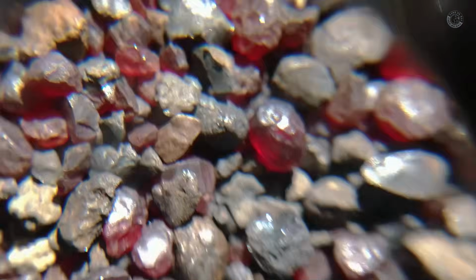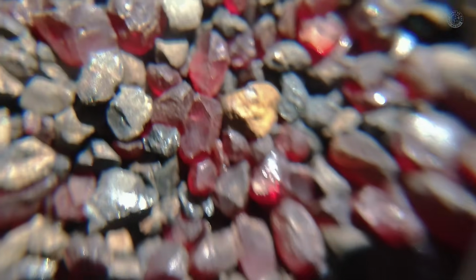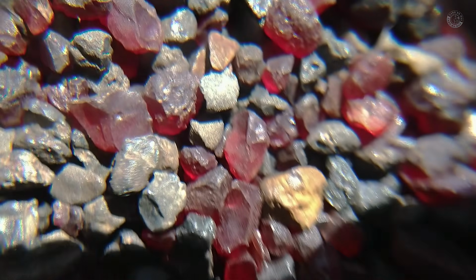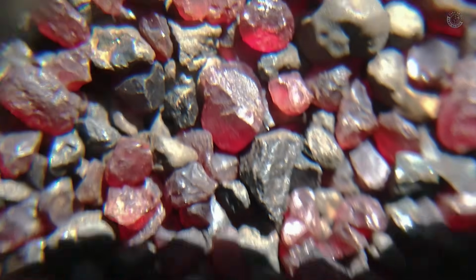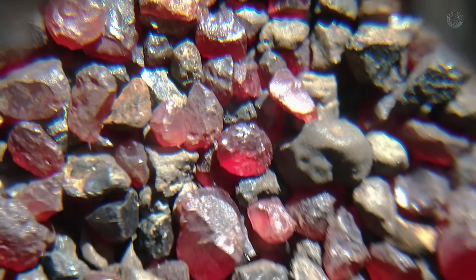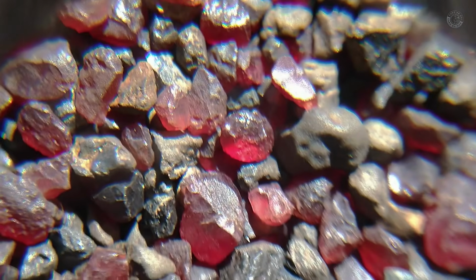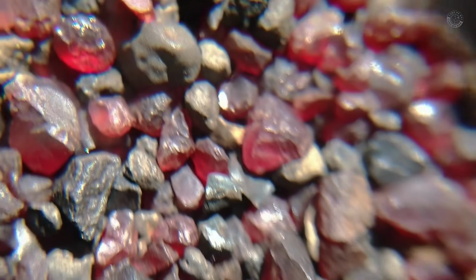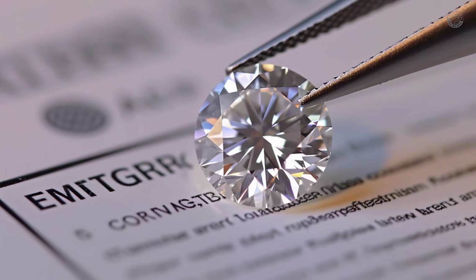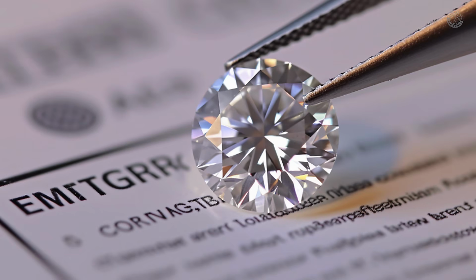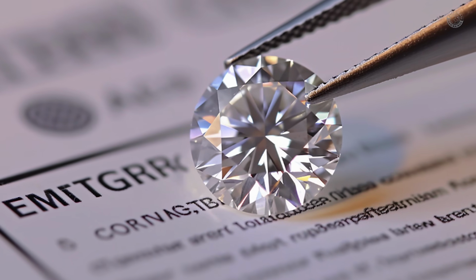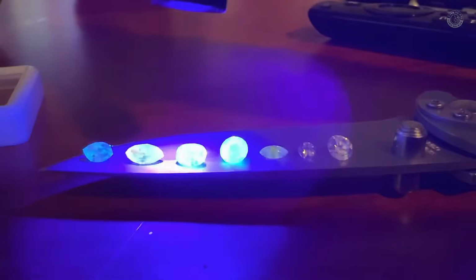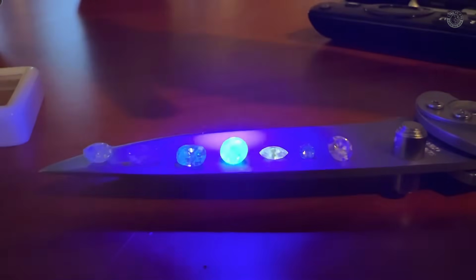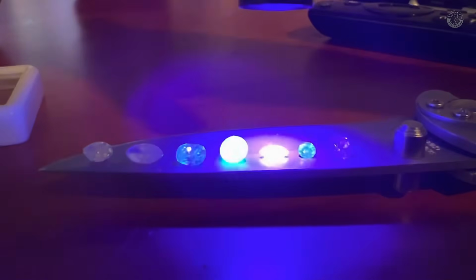Think of a practical example. You pick up a rough pebble from river gravel. It survives the fire test. At that point, it could be diamond, but also sapphire or moissanite. Then you scratch a piece of glass and the line is clear. Again, it could be diamond, but also moissanite. Finally, you do the density test and get a value around 3.52. Now the margin of error drops drastically because moissanite would read differently and sapphire would be over 3.9. The combination of these three steps is what brings confidence and reduces the risk of being fooled.